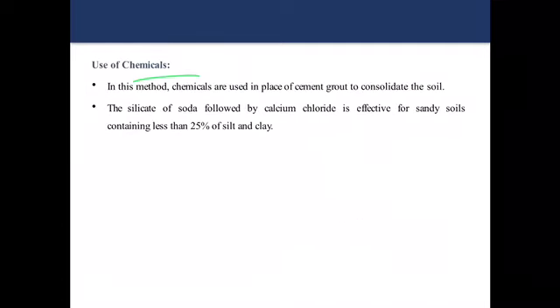The last method is the use of chemicals. Sometimes we can mix some of the chemicals with the soils to improve the stability of the soil instead of using the cement grouting to consolidate the soil. Most popularly silicate of soda followed by the calcium chloride, it acts as the effective admixture in stabilizing this soil. That will be particularly used in the sandy soil which is containing the less than 25% of the silts and clay.